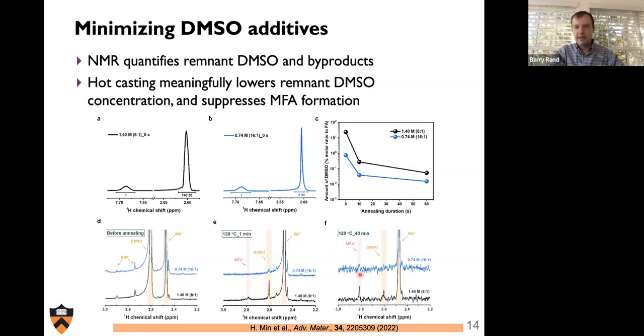At 40 minutes, the film with lower DMSO loading has completely eliminated the DMSO peak, but the one with higher loading of DMSO, it's not gone yet, even after 40 minutes at 120 C. And the MFA peak has notably grown. The MFA peak at this time with the lower DMSO loading is now just starting to be present, but it's also kind of like a hard sell to say it's there in considerable quantities.